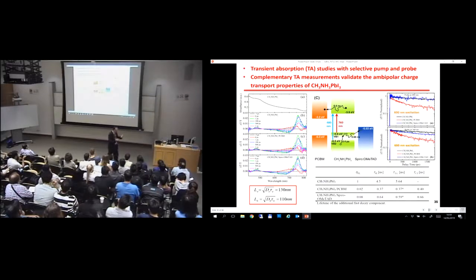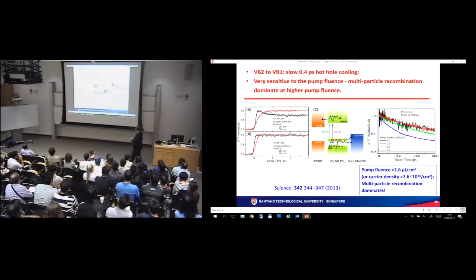And having a material that has relatively balanced electron and hole diffusion lengths, now that is pretty peculiar, especially for a solution process material. You usually don't see this kind of material. So this is actually the key finding that's reported in that paper. That's the reason why your solar cell works so well in different types of configuration.